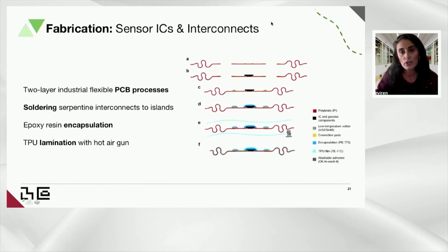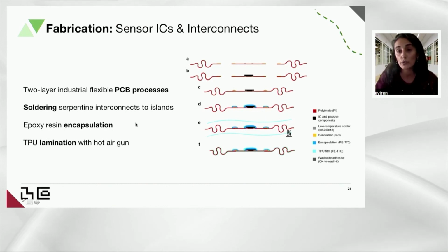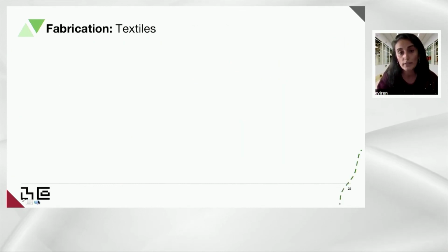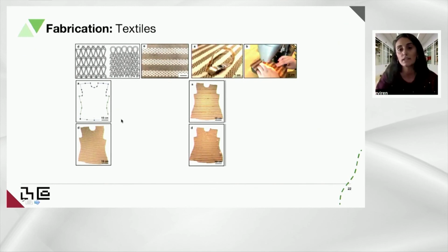And in terms of fabrication, we use 2 layers of industrial flexible PCB boards, where we use soldering serpentine interconnects to the islands where the off-the-shelf electronics are on top. We also use epoxy resin for encapsulation, and polyurethane lamination with a hot air gun. And after this manufacturing, we use the textile to embed the electronics inside, as you can see from here.